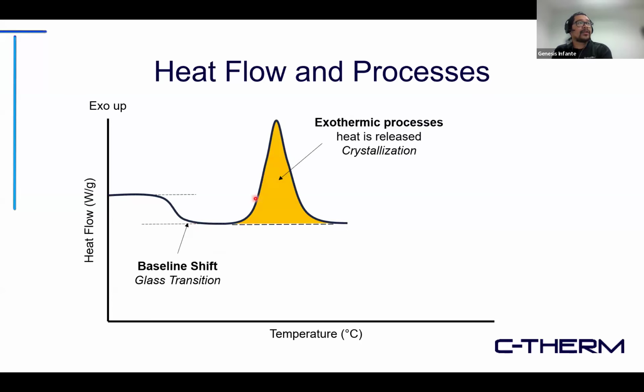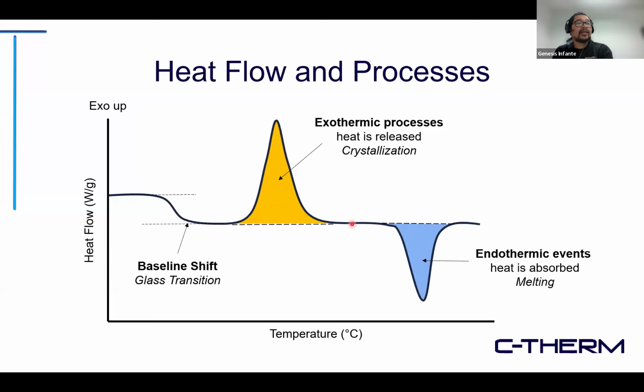Something like an exothermic process can generate a graph looking like this, where you can see a significant increase of the heat flow generated from something like a chemical reaction or a crystallization event, where heat is released and the detector is receiving a signal where now there's an added heat flow occurring in the system. Because we have the exo up directionality in our graph, you can see that it is an exothermic event. And of course, the opposite of that would be an endothermic event, where heat is typically absorbed. This is typically associated with something like a melting event, but for polymers, typically it's going to be a melt.